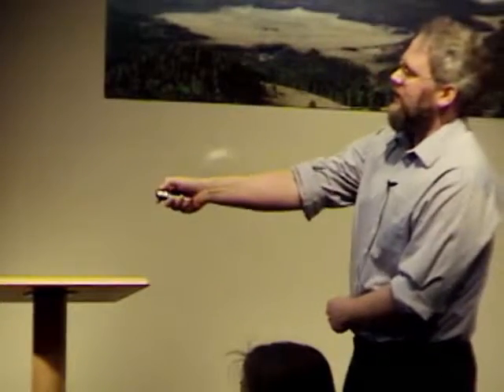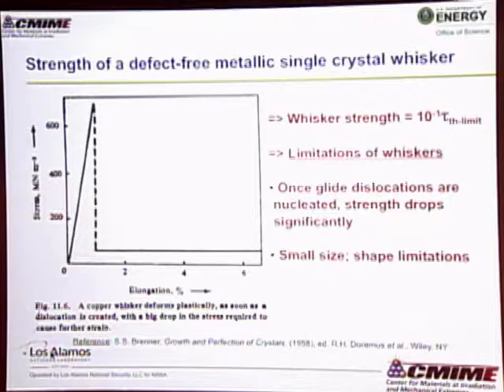In fact, it was tested back in 1958 on perfect copper whiskers, which were very, very fine little wires that have absolutely no defects. They're perfect material. And what happens when you load this, so this is stress, this is how hard you're pulling on it. You pull on it, you pull on it, you pull on it, and then all of a sudden it drops and the strength is very, very low as you continue to pull on it. And the reason for that is this material that had no defects right here, you hit this stress and then we generate defects, and those defects limit the strength for the rest of the deformation. So this is one way of looking at it.